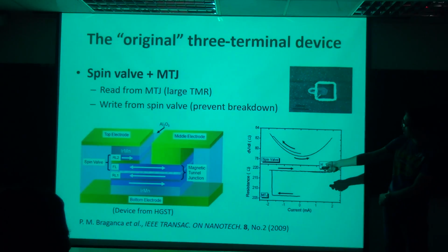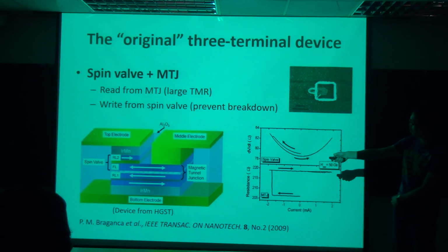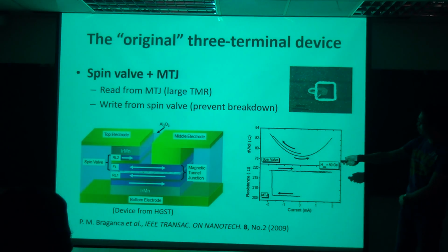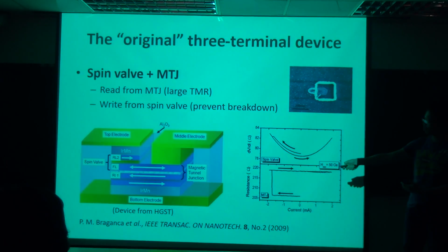So the idea is that for the spin valve part, you send current this way through the top electrode to the middle electrode, and you will have spin torque coming from this layer injected into this free layer to do the switching. And once it's switched, then you do the read out using the middle electrode and the bottom electrode.